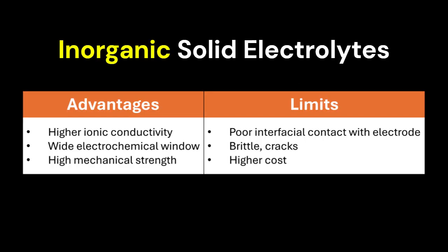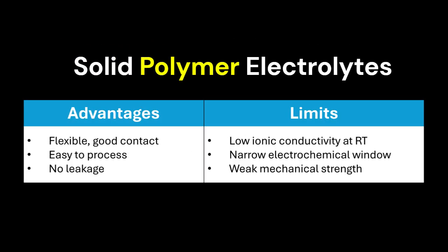Why do we choose polymers? Solid electrolytes can be broadly classified into two types, inorganic and polymer. Inorganic electrolytes generally offer higher ionic conductivity, but their rigidity often results in poor interfacial contact with the electrodes. In addition, cracks can form because they cannot effectively accommodate the stress caused by volume changes during charging. In contrast, polymer electrolytes are soft, flexible, and easy to process, allowing better contact with the electrodes. These advantages make polymers a promising choice for solid-state batteries.